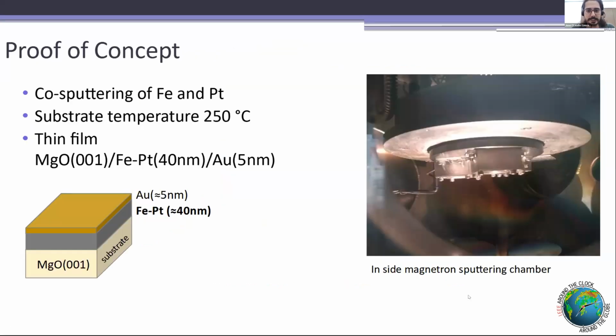So as a proof of concept, we put it inside the chamber and did the first co-deposition of iron platinum with a temperature of 250 Celsius. We deposited thin films of 40 nanometers and a cap layer of gold of 5 nanometers. And after the deposition, it proved that this works with temperature, because after the depositions, the magnetic field continued the same. We did not have any problems; the magnetic field was constant along all the depositions.